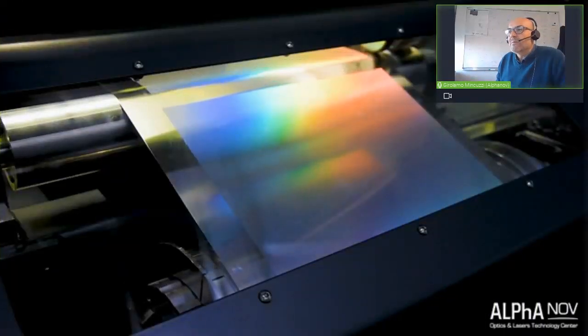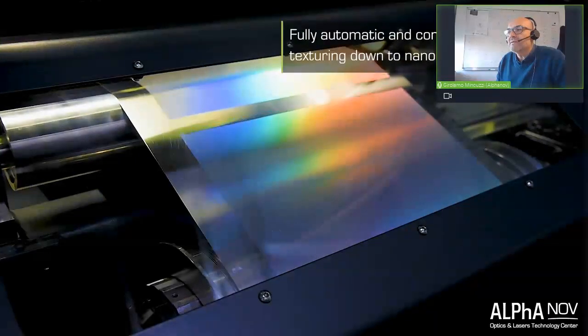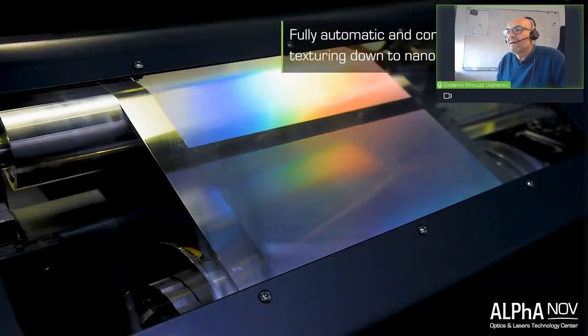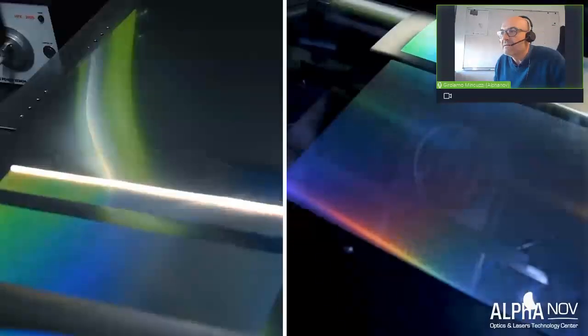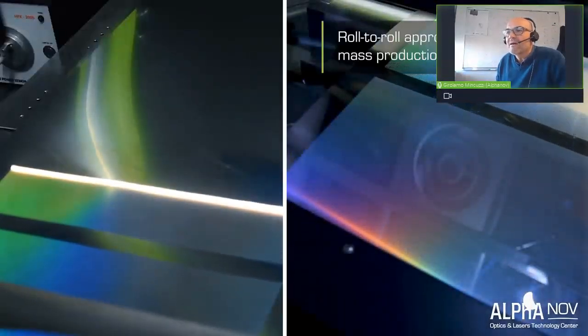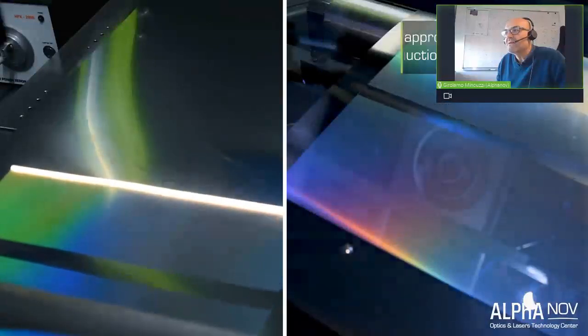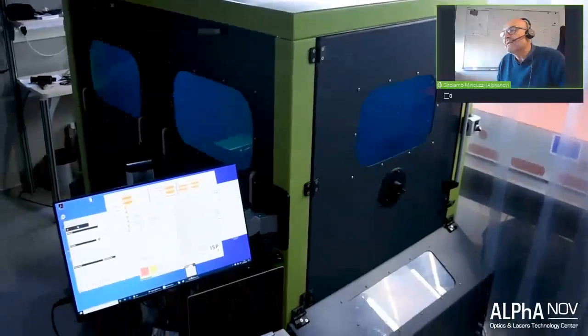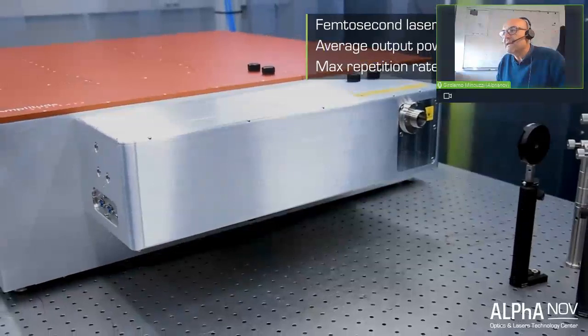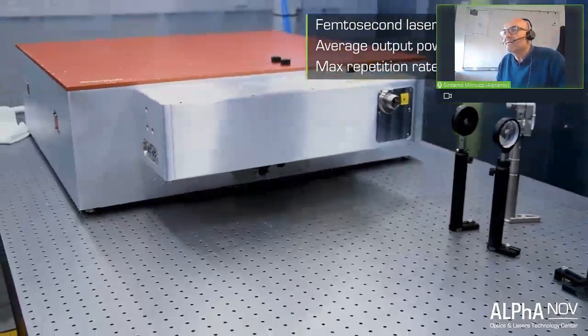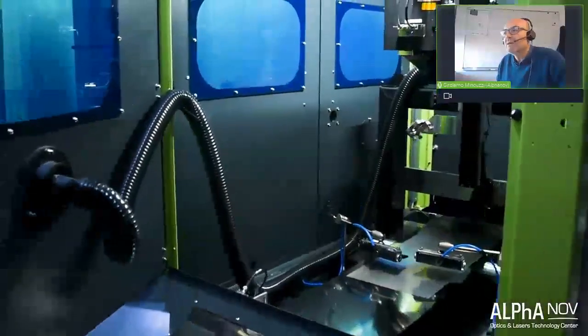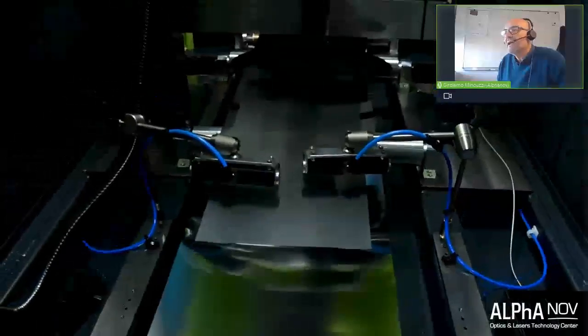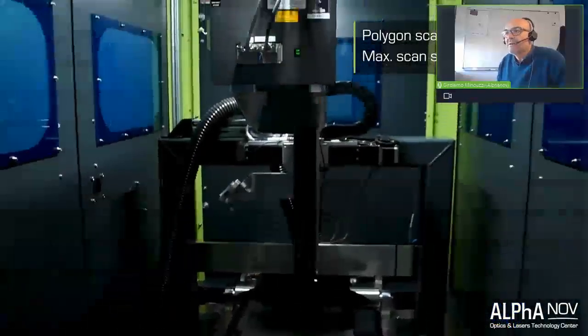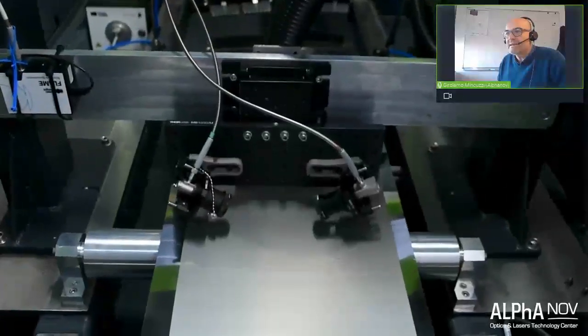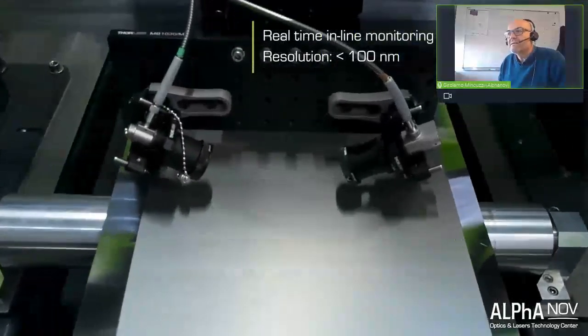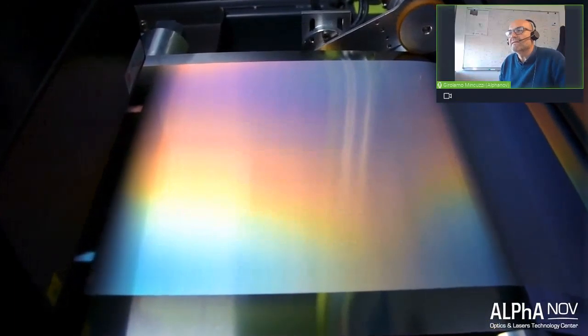Here you see the process. The part that has been textured is identified by this dispersive effect, so it's a rainbow color you see. On the left you see the laser, and on the right you see the speed of the process. It's quite fast. Here you see the laser that we implemented in the machine, and this is the scanner we use, and here you see the inline monitoring system.